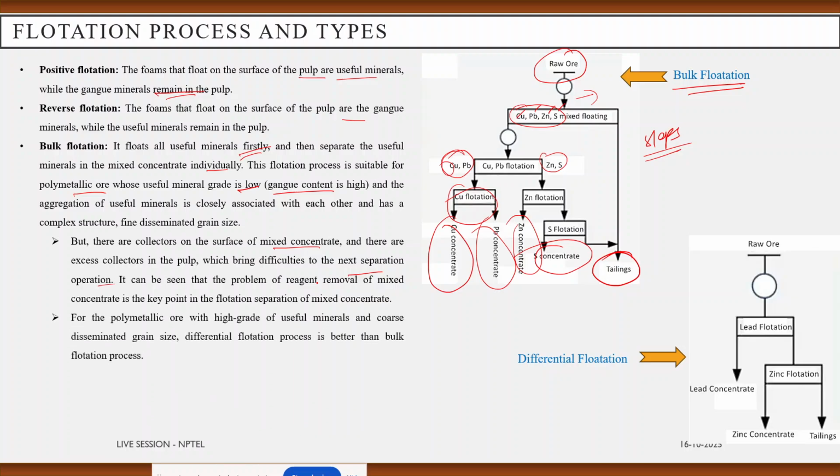So these are some disadvantages of the bulk flotation. When you are handling polymetallic ore with high grade useful minerals and coarser disseminated grain size, then we recommend that the differential flotation process should be followed for better separation than the bulk flotation process.